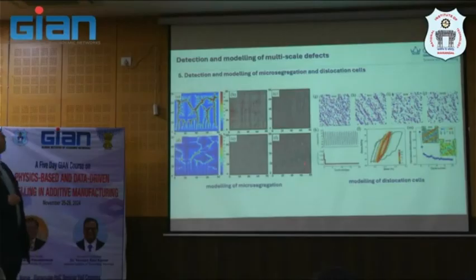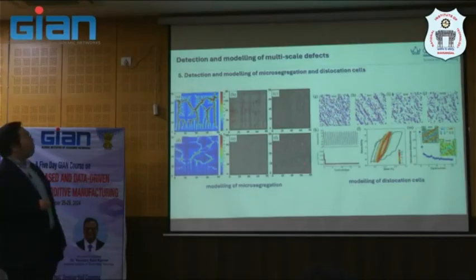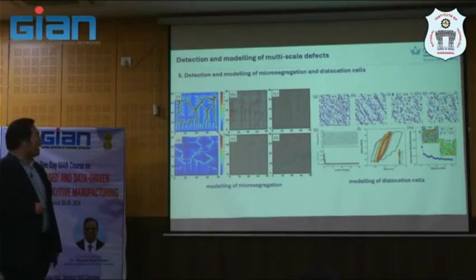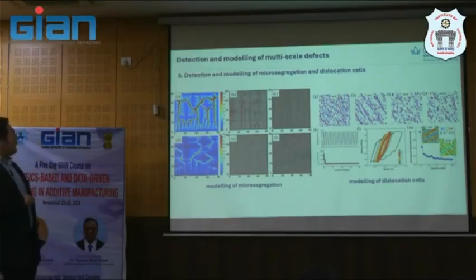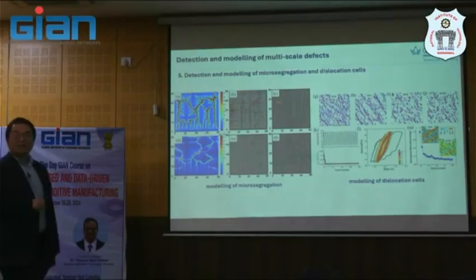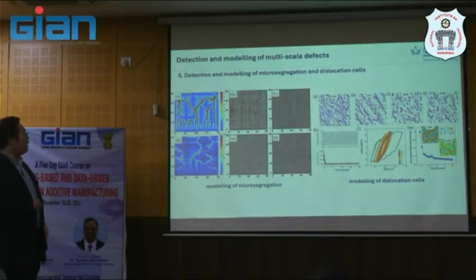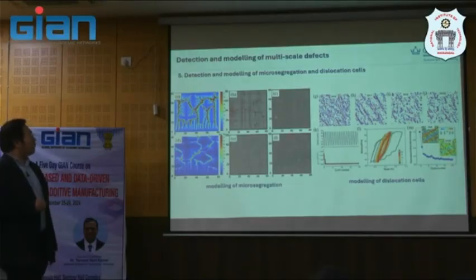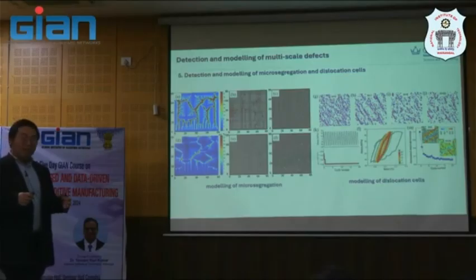And next one is about how we can model the microsegregation, which I think we showed you a lot yesterday already on the dendritic growth, and then you see the segregation profile here. And this is not an artifact. This is actually real. This is induced by the process, and we will have an example with deeper insight into the metallurgy of nickel-based superalloy in the next lecture.